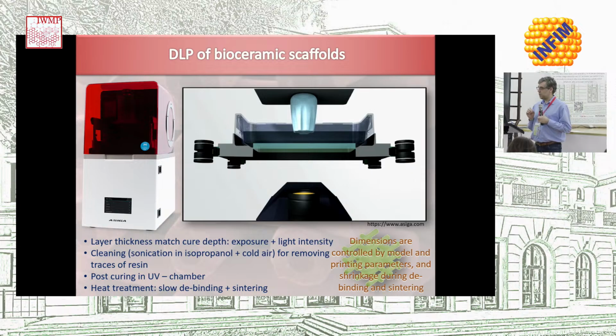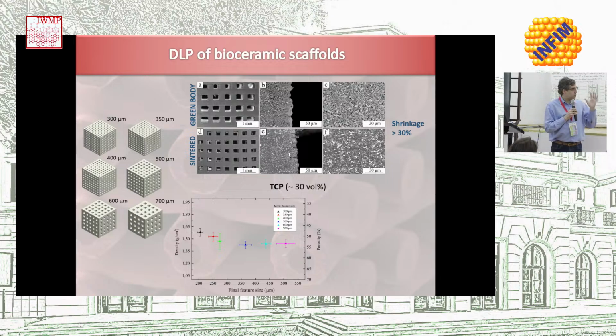Another thing that has to be taken into account when using DLP, and when you are using ceramic powders, for example, or any other type of powders in suspension, is that the particles will also scatter light, so there will be a deviation of your part from the size that you selected in the model, so from the image that you are projecting, because light will scatter around each of the pixels. Nonetheless, if you take into account all those issues, you can produce nice bioceramic scaffolds, as I'm showing you here. You can see that there's a large shrinkage between the green body and the sintered structure. And also, you can see the actual individual layers of the printing process on the external surfaces of the scaffold.